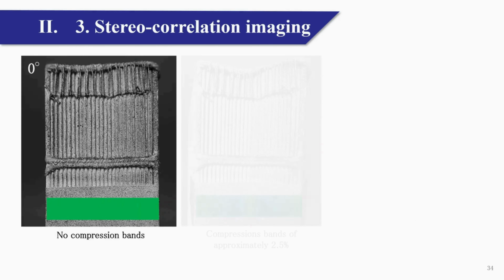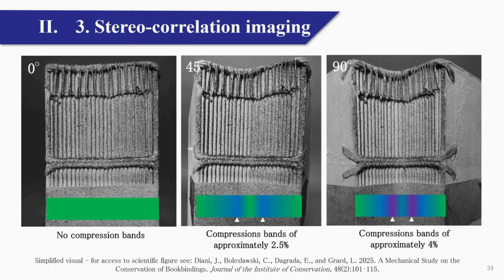The book model was positioned upright and opened at 45 degrees and 90 degrees. A compression of around 2.5% to 4% was determined for the 45 degree and 90 degree openings. You can see that the signature folds are closer together near the compression bands.